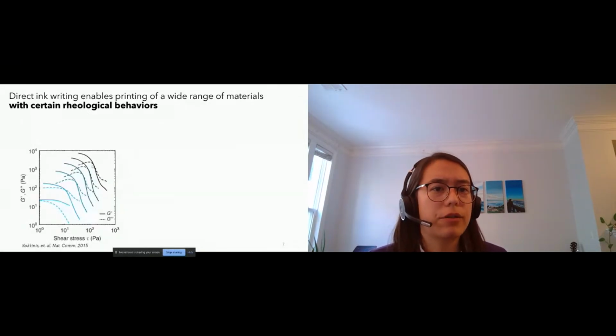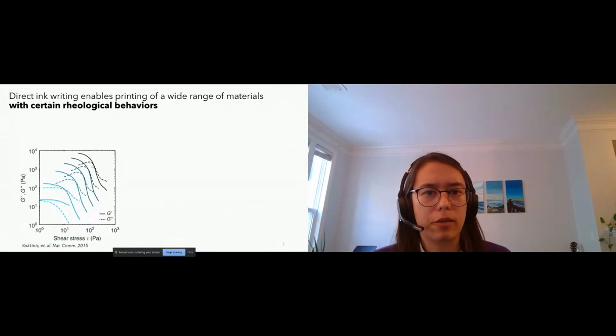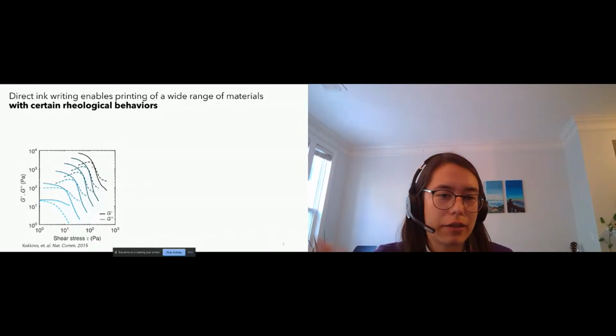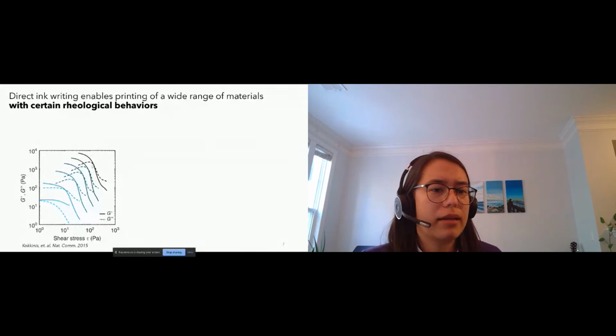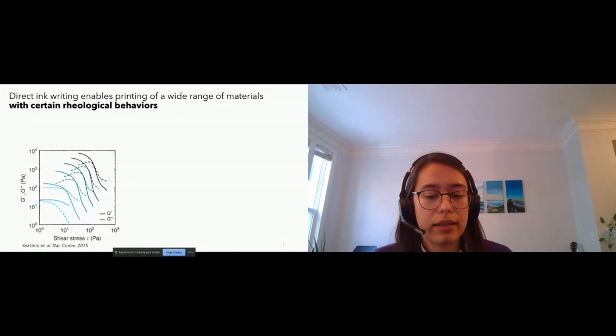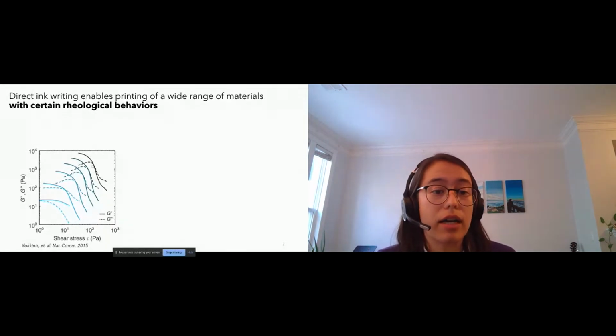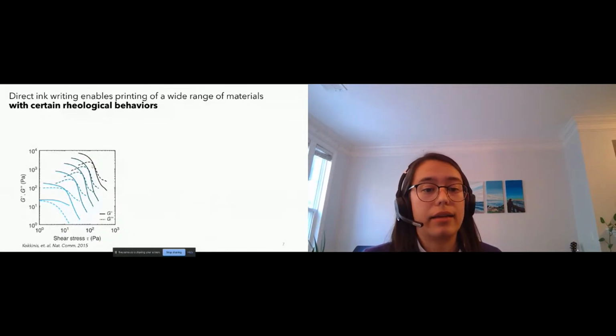Now, the limitation with direct ink writing is that you can only print inks that have a certain range of rheological behaviors. They have to flow in a certain way. What we're looking at here is a plot of a variety of different materials where we've plotted the shear modulus, the storage modulus, and the loss modulus as a function of the shear stress imposed on that ink.